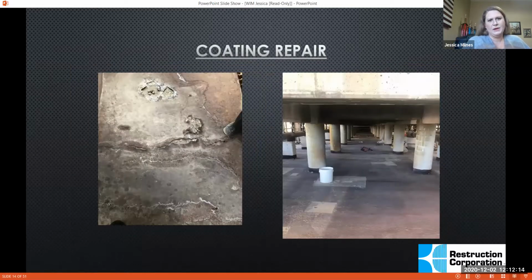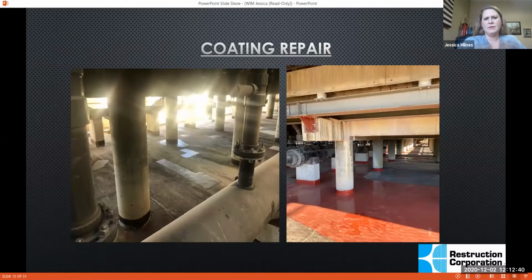So here's an up close of that coating. And then what we're showing here is that sometimes if we catch it early enough, and we were able to catch a lot of it widespread across here early enough, the concrete wasn't bad underneath. So it's basically just removing the coating and replacing the coating. That's what we did there. And then here's a big overview of how you can see that we just removed the bad spots, and it's a mining environment, so no one really cares that much how beautiful it is when we're done.